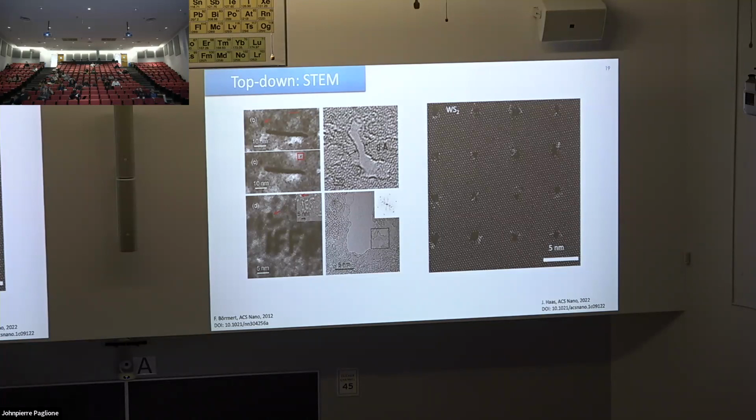If you're not using this as the active material, but only as a gating material, I don't know how a magnetic field would affect this material itself. But at least for the graphene with holes in it, we saw that it has a big effect. You have states living around the circles and so on, and you get commensurability. The theory was based on removing individual atoms, right? Yeah. So why are you then creating larger circles, rather than just shooting one out with a single spot size? We basically don't have that control. The theory was not even individual atoms, maybe it's like 10 atoms or something like that. Still much more than we can do, but you do need a certain size of the holes, even in theory, to get a mix of the superlattice and a quantum confinement effect. So between two holes, it matters how little graphene is left as well.